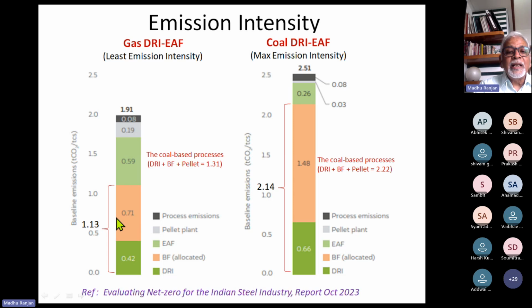In the gas DRI EAF also, up to the iron stage, the CO2 emission is about 1.31, and around 0.6 tons of CO2 is responsible for the steel making portion. In the coal DRI EAF, the coal-based DRI process, the iron making is 2.22 and only around 0.29 in the steel making stage. Okay. So one has to make a balance between which process is more suitable going forward in the future.